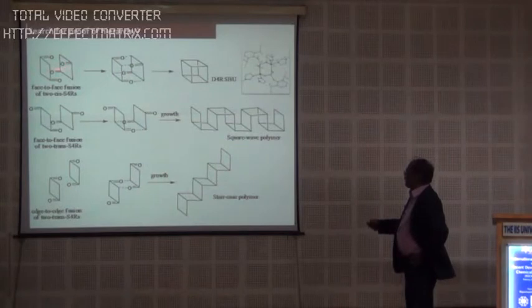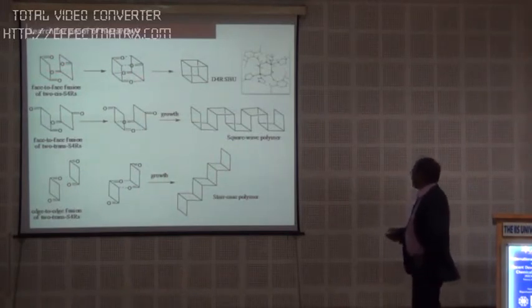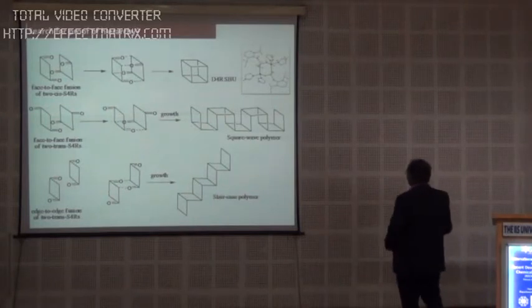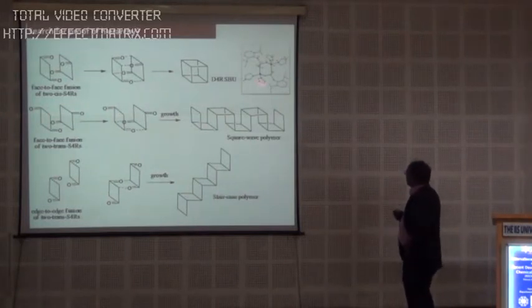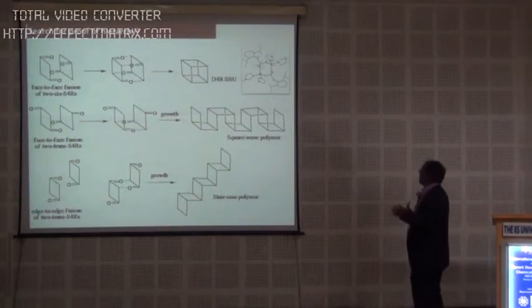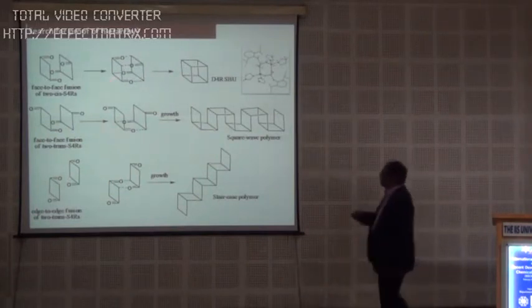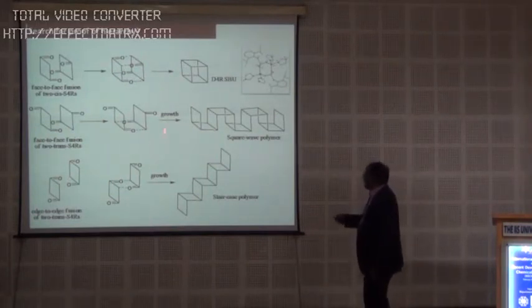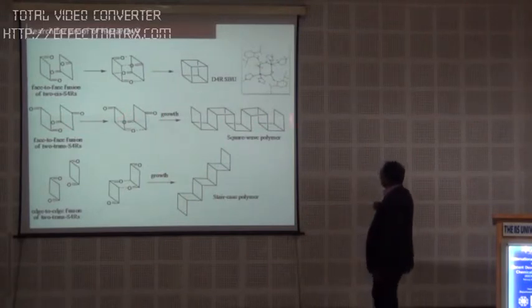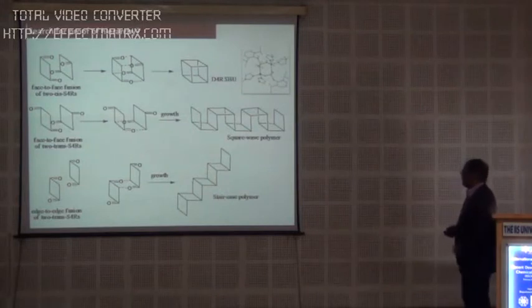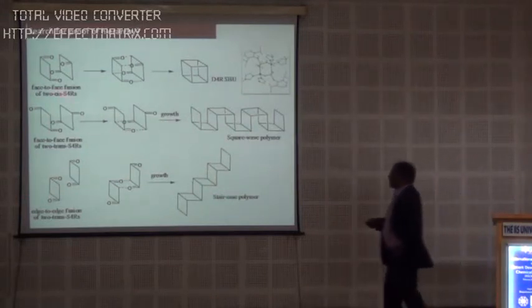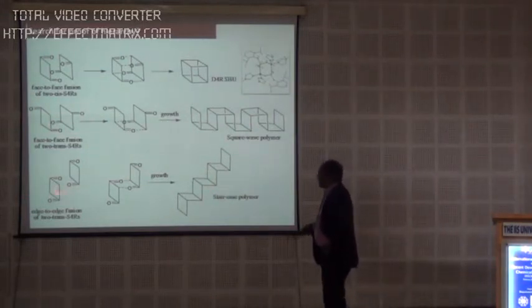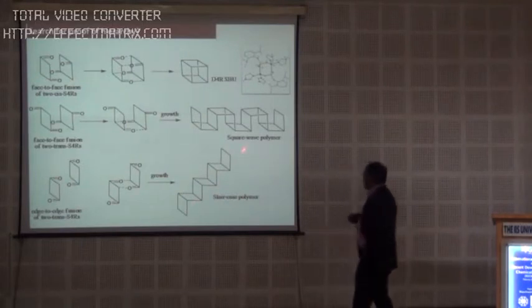Either you can have a face-to-face dimer formation to give the usual suspect, namely the double 4 ring, which we get in 99% of all our reactions. But if this were to be the structure, which is for symmetry reasons more stable, one would not actually close the cube, one would rather get a tub. These tubs could then be placed next to each other and form something like a square wave polymer, but a two-dimensional polymer. Or it's too much to expect that they will come only face to face, they can come even randomly and can form stair-case polymers.